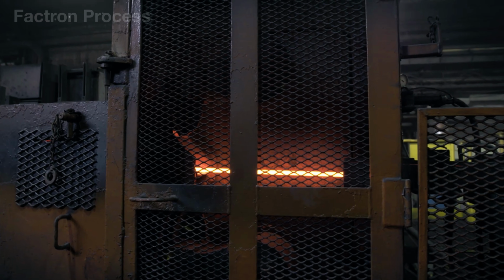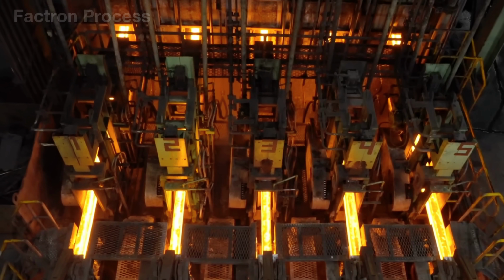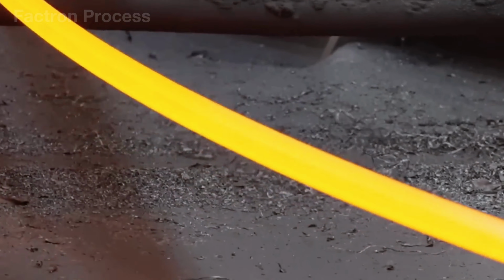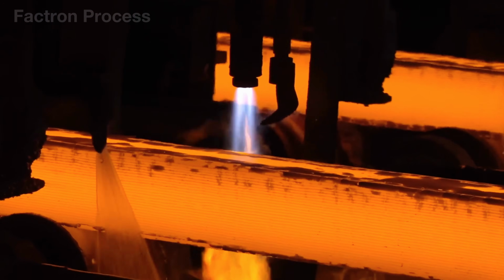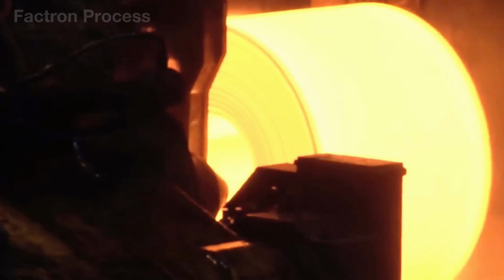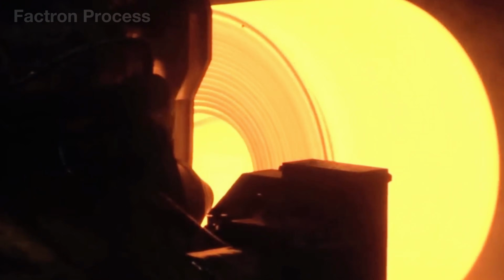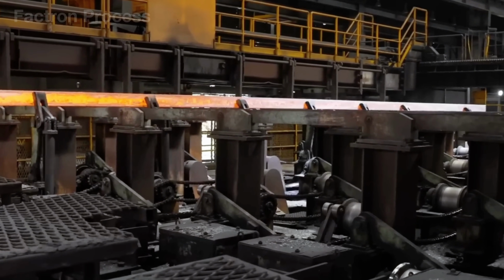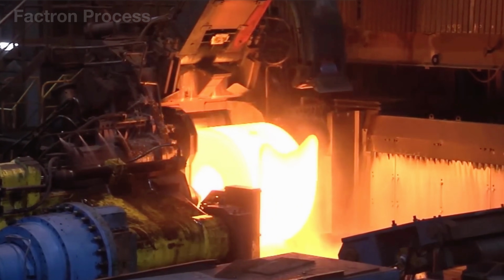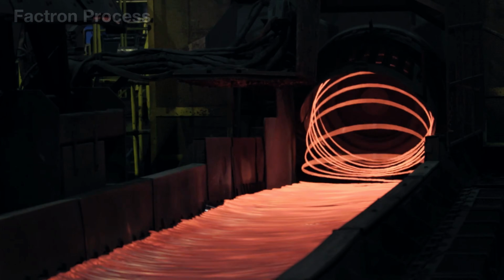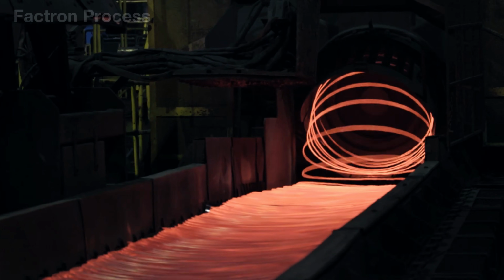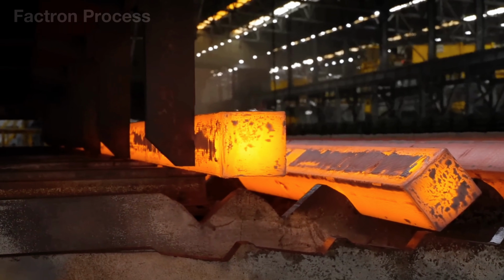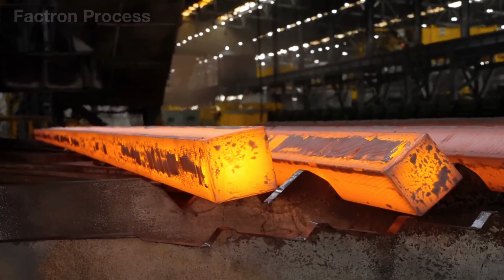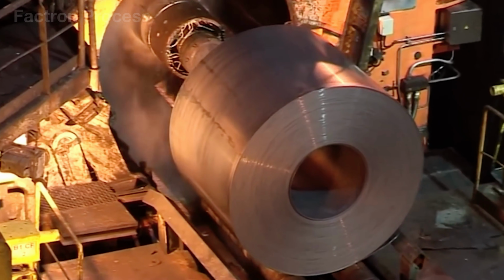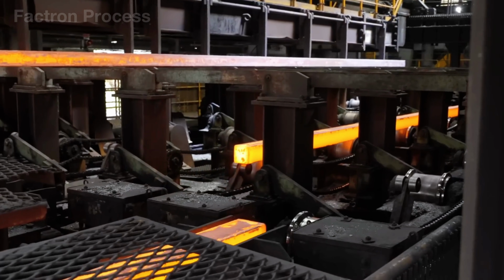Under this immense pressure, the material is transformed into different products according to market demand. Slabs become steel plates or hot-rolled coils, billets are rolled into steel bars or wire rod, while larger blooms are formed into structural beams or heavy-duty rails. An automated laser measurement system continuously controls the roll gap, keeping thickness deviations below 15 microns and completing the steel's remarkable journey of rebirth. As the glowing steel strips leave the rolling mill, they are immediately cooled under controlled conditions